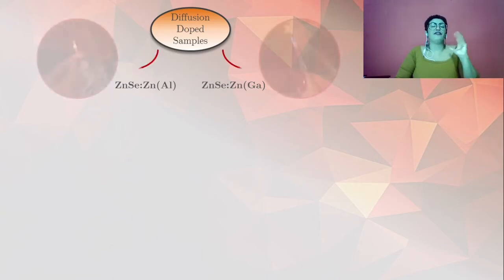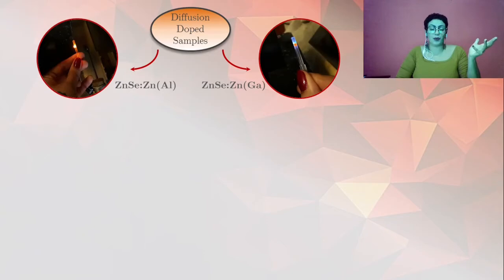impurities on the samples. Two samples prepared from the ZnSe mother sample were doped with aluminum and gallium separately by diffusion method in a muffle furnace at 600 Celsius degrees for 100 hours in vacuum-sealed quartz ampoules. And finally, we got luminescent samples. The aluminum-doped sample showed a strong luminescence under UV laser excitation, and the gallium-doped sample showed a less intense luminescence.